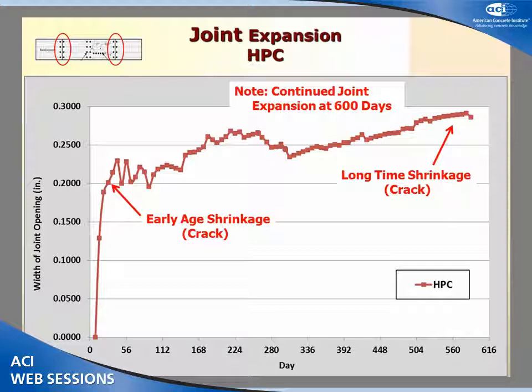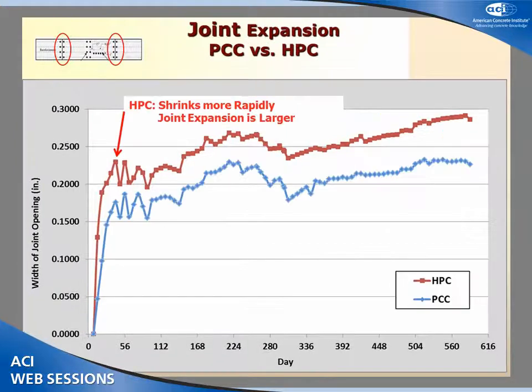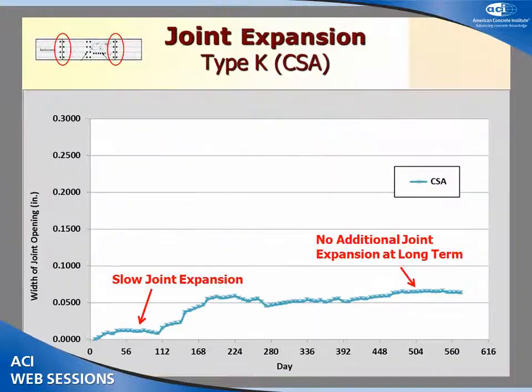This graph shows the high performance concrete, where again you can see the early age shrinkage or joint expansion, and also it continued for a long time. After 600 days we still had joint expansion for this type of concrete. In this graph I wanted to compare the high performance concrete and Portland cement concrete, and as you can see the shrinkage of the high performance concrete is more rapid than the Portland cement concrete or normal concrete, and also the joint expansion is wider or larger than normal Portland cement concrete.